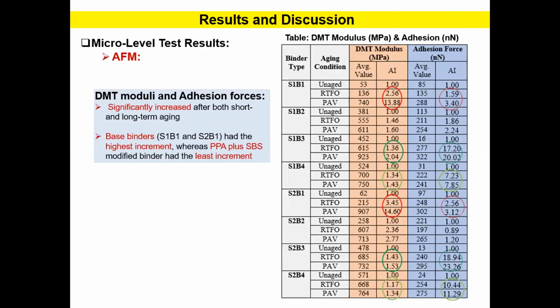In this table, I summarized the DMT modulus and adhesion force values obtained from AFM, and along with their average value, I calculated the aging indexes to compare and show the changes and the severity of aging effect on the DMT modulus and adhesion force values. The result shows that here the red circle is the most severe one, and you can see the control binder from both sources had the highest increment in both modulus and adhesion force values, whereas the SBS and PPA plus SBS modified asphalt binder had the least increment.